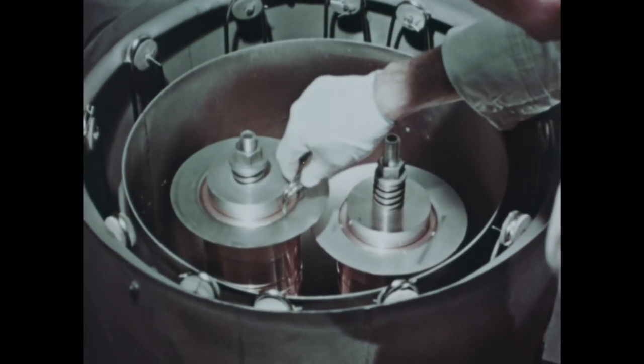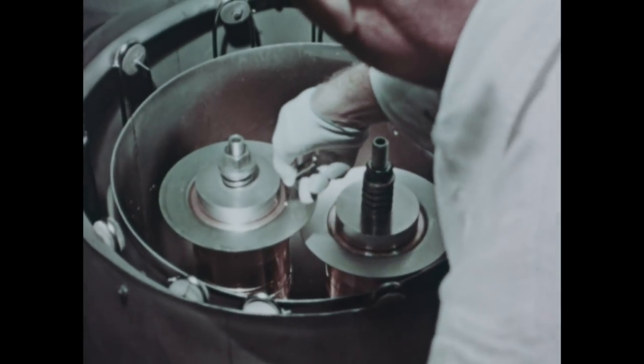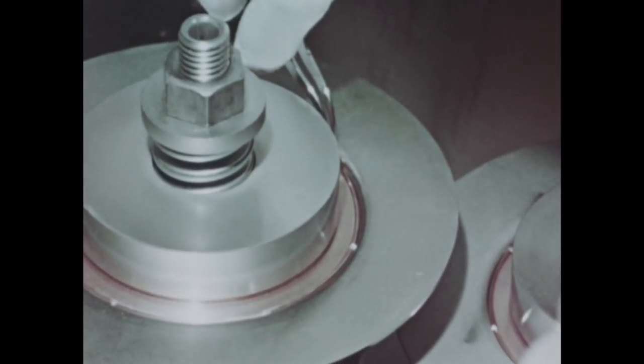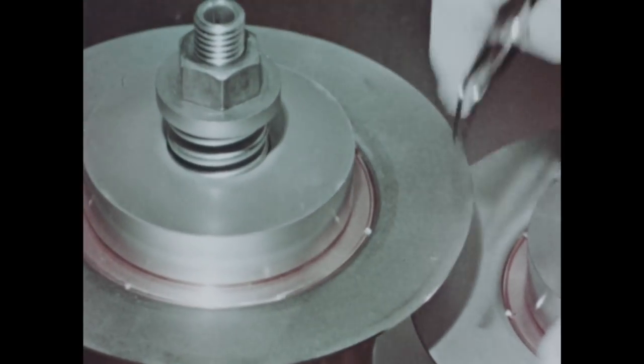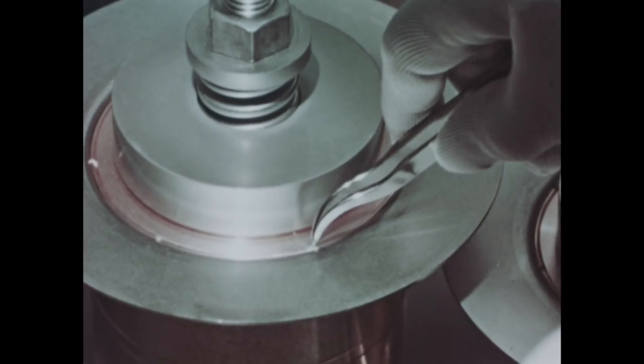Connection flanges, which are welded together to connect the 10-foot sections on the girder assembly, are placed on with alloy to braze them to the coupler. Care must be taken to make sure the alloy does not run onto the surface of the flange and interfere with welding.